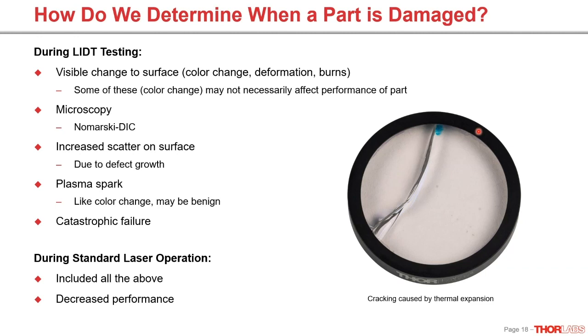One other method is you can look for scatter on the surface. Obviously, any of these pictures of damaged optics I've showed you would have significantly increased scatter over the undamaged coating. So that's one method. You can also look for a plasma spark, which is just a bright flash. Something like that can be detected. But like the color change, that may occasionally not be problematic. If you're ejecting a particle, sometimes you will get a flash. But if the optic is still performing as it should be, you may be able to keep using it.